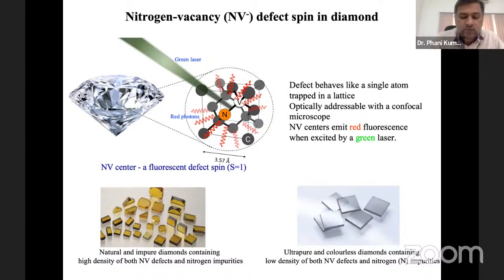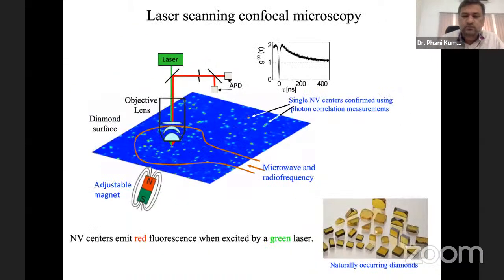The kind of diamond samples which we use in our lab typically look like this, as shown in this slide here. They are of 2 types typically. One is the natural and impure diamonds, which contain a very high density of NV defects and nitrogen impurities. These nitrogen impurities are just the P1 centers, which Dr. Pavan was talking about. And we also have these ultra pure and colorless diamonds, which have a very low density of NV defects and nitrogen impurities. If you take one of these yellow samples, they get this color because of the large presence of nitrogen. So if you put this diamond sample in a confocal microscope, and take a confocal scan of a certain region of the sample, then you see these bright spots, and these are all the single fluorescent centers.